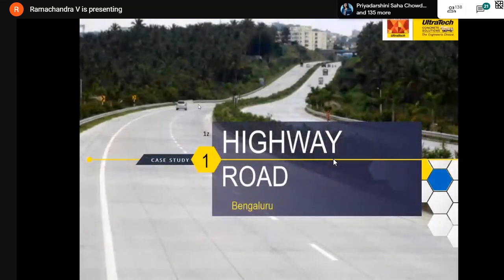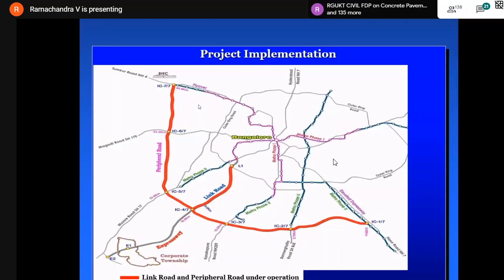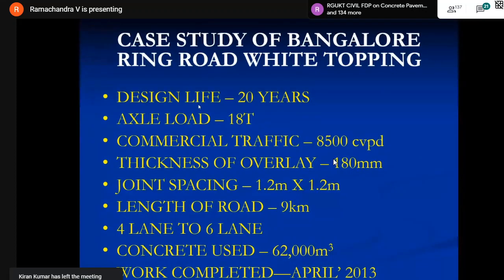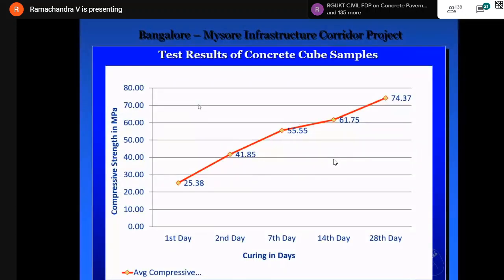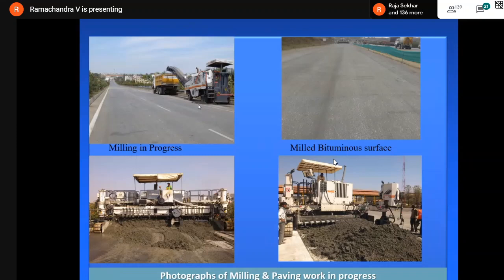Now, let us take the example of one highway road. This is the outer ring road in Bangalore, which is called as a NICE road. NICE stands for Nandi Infrastructure Corridor Enterprises Road. This is about 10 kilometers and the design life is 20 years. Very heavy traffic on this, more than 8,500 commercial vehicles per day. Cars and other vehicles are not counted at all. Commercial vehicles are counted. Joint spacing is 1.2 by 1.2 meters. Thickness was designed as 180 millimeters. You can see the 28 day strength of this concrete was 75 MPa. 1 day strength was 25. That is the beauty of this.